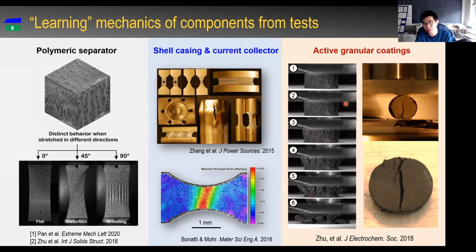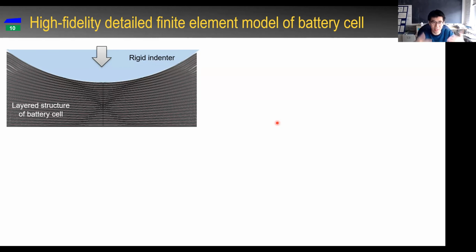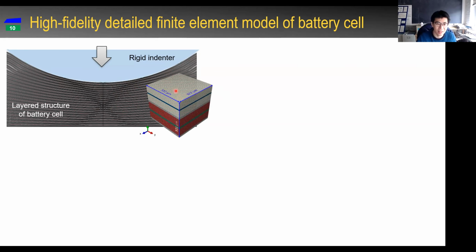And recently, my collaborators and I tested the active granular material. Actually, this is the core material in this battery system because this is where the reactions happen, at the interfaces. With this testing, we can calibrate models and implement these mechanics into the RVE, the smallest unit cell. And this is something we developed. It's a cross-section of a model. We simply put layers together and give the mechanics to each layer. The smallest unit is like this, and each layer means each component material, and we give the constitutive laws to each material.